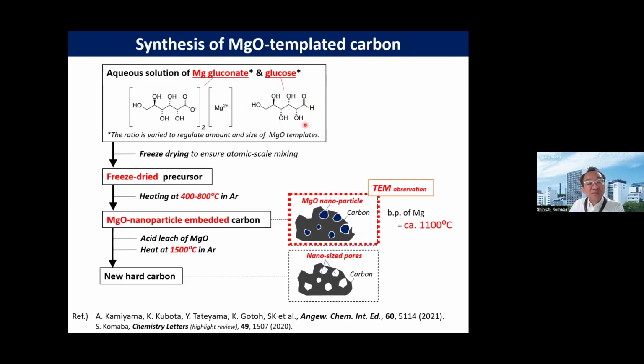You see, the starting material is not only glucose, but it was mixed with magnesium gluconate, then freeze dried to make sure of an atomic scale, homogeneous mixture, then heat treatment at intermediate temperature, and then finally carbonization to have hard carbon. Because of the magnesium containing starting material, after the heat treatment, we have not only the carbon matrix, but also highly dispersed magnesium oxide in the carbon network. And during post-heat treatment at 1500 degrees C,